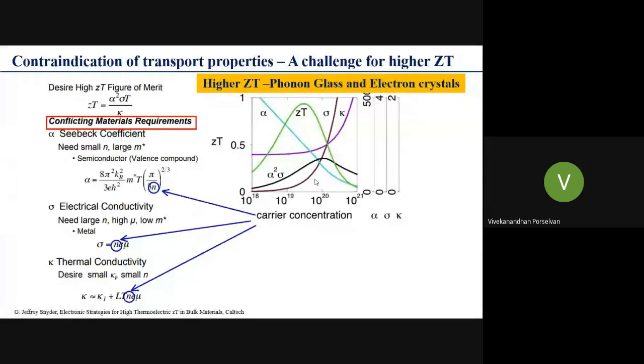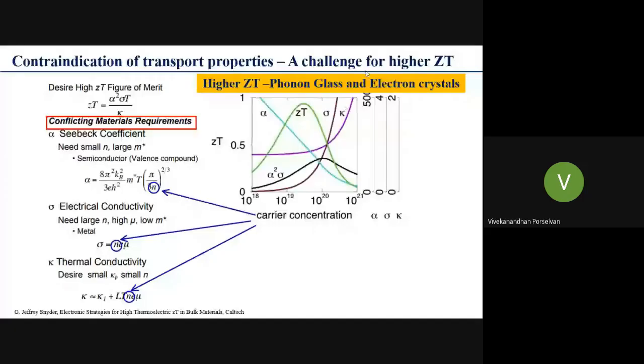Somewhere between 10^19 and 10^20 carrier concentration, we can trade off, or make the optimum electrical conductivity, thermal conductivity, and Seebeck coefficient to achieve a high ZT value. This kind of optimization has to be done in the thermoelectric material. This particular range, in which we get the higher value, lies between 10^19 and 10^20, which we designate as the semiconductor range. That is why a semiconductor is a material with the potential to deliver a superior ZT.